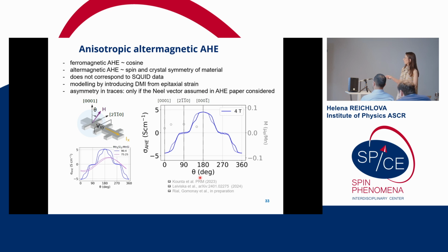And here I will just mention one more thing, that the anomalous Hall effect is also highly anisotropic compared to, let's say, ferromagnets, where we would expect some cosine-like dependency of the anomalous Hall effect. Here, in this case, when we do the angular dependency, we rotate the magnetic field from out of plane to in plane. This is the signal which we are measuring. And you see that there are some characteristic features. First is the asymmetry of the trace there and back, clockwise and anti-clockwise, and also these highly anisotropic plateaus in the characteristic shapes. And here, without going into too many details, there are two things to note.